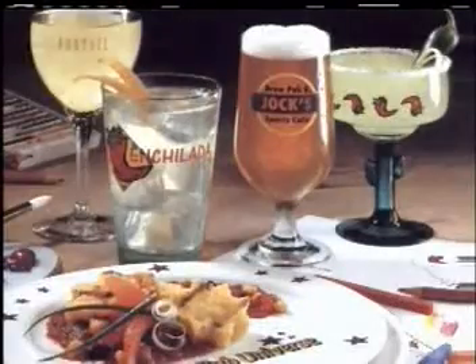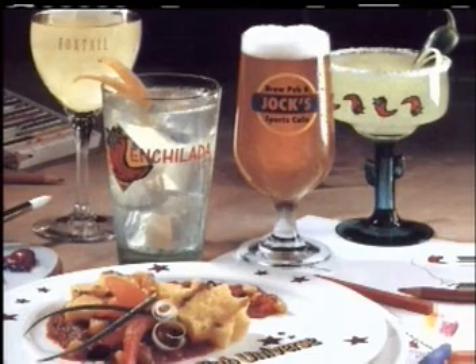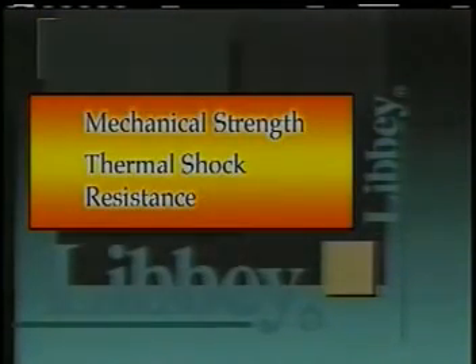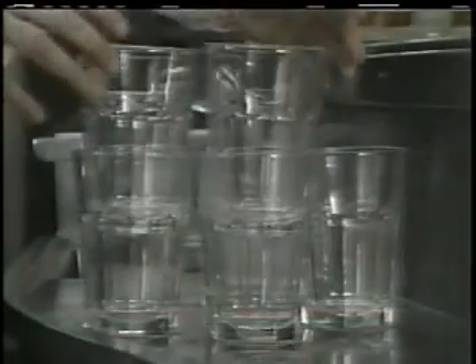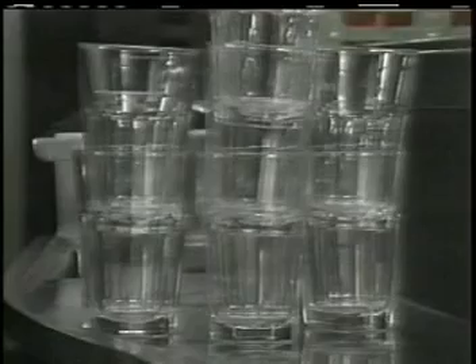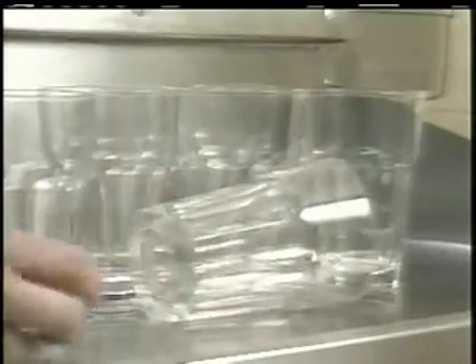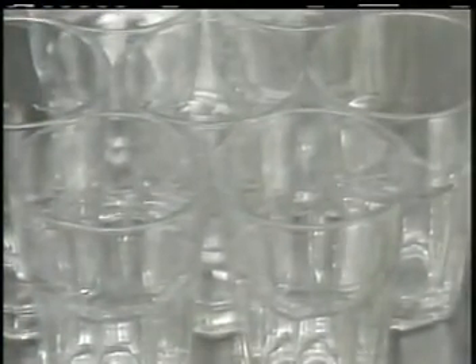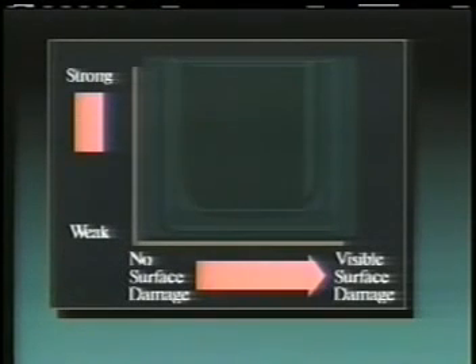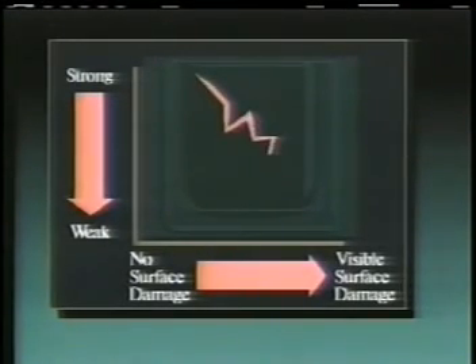Let's take a look at exactly what the forces are any piece of glass has to withstand in the modern food service operation. Generally, glass strength is measured in two areas: mechanical strength and thermal shock resistance. Mechanical strength describes the ability of the glass to withstand impacts, including the kinds of abrasions and scratches we were discussing. Also, when glasses are stacked, not too gently at times, when they're jostled against one another, when they tip over, and when they are dragged or scuffed across a hard countertop or sink, their surfaces are damaged. This chart shows how as surface flaws increase, glass strength is reduced. As you can see, the weakening effect is dramatic.